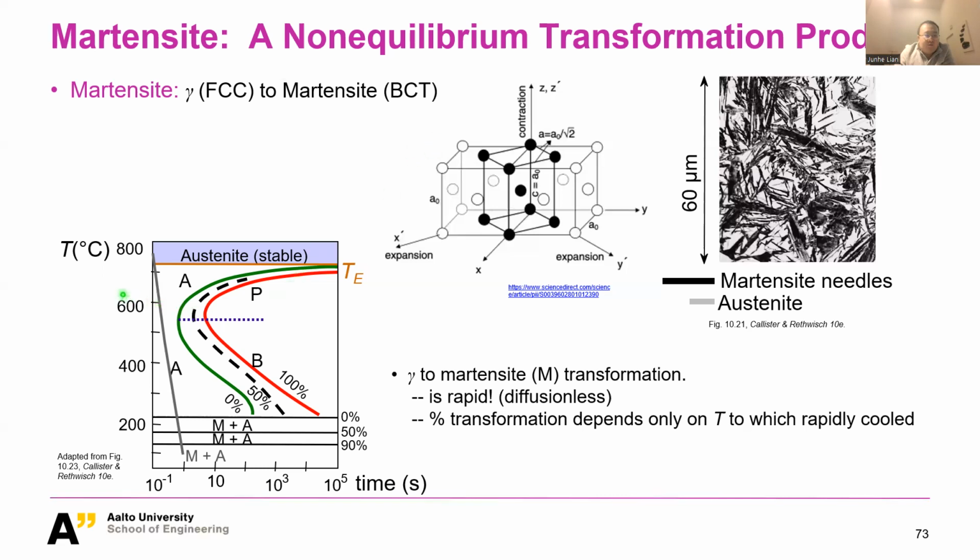Well, during lecture, I think you remember, we showed you if we want to cool down austenite into room temperature from 800 something, when we use a rather small level of undercooling, which means a rather small delta T, you will produce pearlite, and with small delta T you have coarse pearlite, and with a rather large delta T you get fine pearlite.